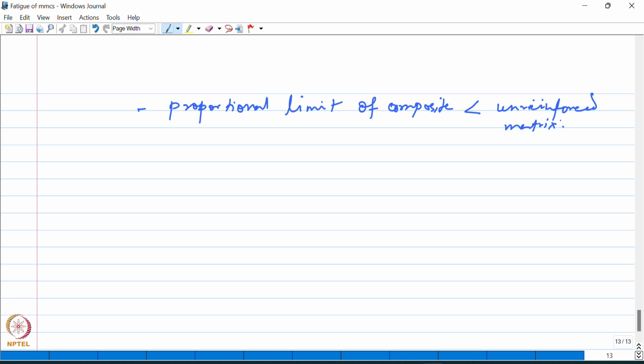Okay, so when you go towards a stress condition when the mean stress is positive, the plastic deformation will occur in the first cycle, but in subsequent cycling it will be generally elastic. But because the elastic strains and thus the total strain also, because the total strain is a summation of elastic and plastic strain, are lower in the composite, improvements in the fatigue life are observed for composite materials. Okay, and that is what you can see from this plot over here when R is equal to 0.1, which is positive.